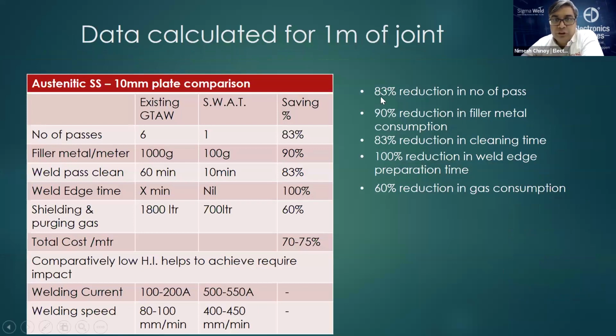So the increase of efficiency goes up to 83%. Filler material saved 90%. You don't have to clean weld passes, so you save 83% there. Weld edge preparation is not required, so 100% of that time is saved. About 60% gas is saved, and total cost per meter can be reduced by about 70 to 75%.